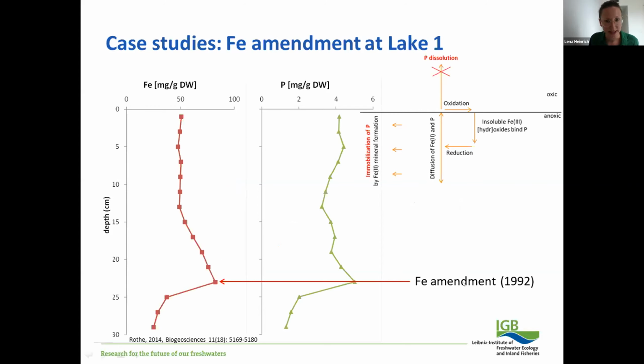After the iron amendment in 1992, the iron and phosphorus contents in the sediment increased and stayed much higher than the background before 1992. The iron-related phosphorus fractions accounted for 80% of the total phosphorus found in the sediment, and Vivianite was identified and it was abundant. And what we see in this sediment is the combined effect of the iron wheel and the phosphorus immobilization by iron. So the iron wheel is active and it is recycling iron to the surface of the sediment. But also the immobilization by two-valent iron is active and it can stabilize phosphorus against the dissolution under anoxic conditions.